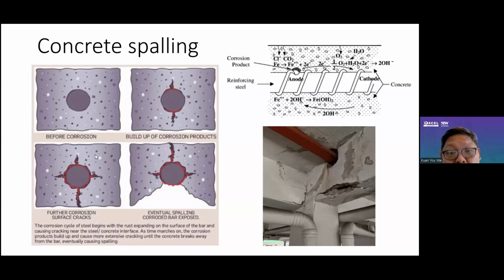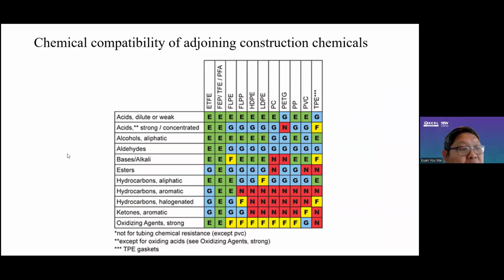So before we waterproof our existing building, we do need to stop the corrosion activity by using sacrificial anode, corrosion inhibitor, and cathodic protection. And whenever we replace waterproof, we need to bear in mind that waterproofs are construction chemicals, and chemicals of different substances are not necessarily compatible with each other. So we need to make sure that whatever new or different product we apply on the existing waterproofing coating or membrane is compatible, so that it doesn't repel and cause premature failure.